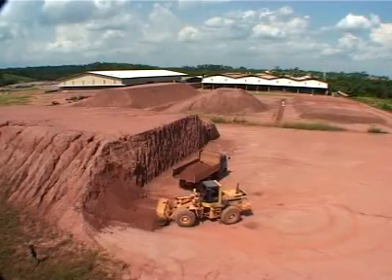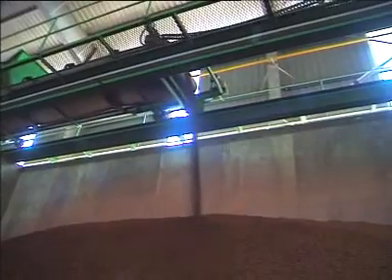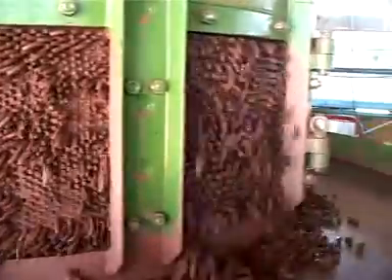The GCI clay roof tile manufacturing process begins with the grinding of the material, which is operated by a set of high-speed rolls. The clay is then moved into a mixing unit where water is added to raise it to the correct moisture content. A mixing process follows, where many tons of pressure allow the stored clay to spread out its water content evenly.